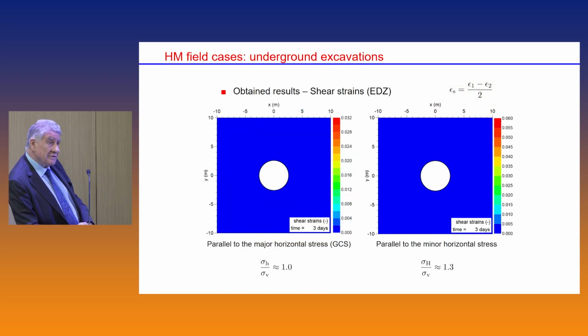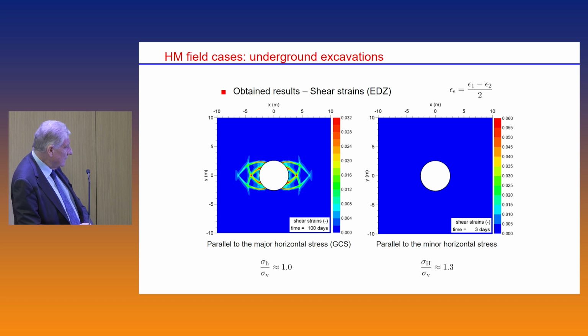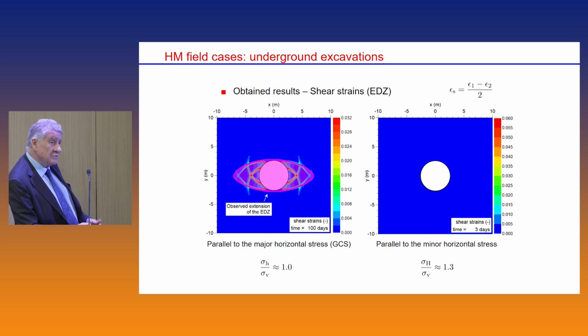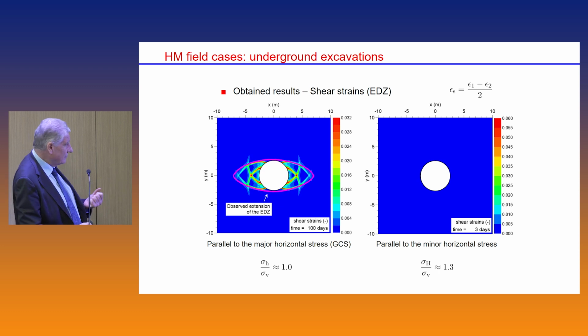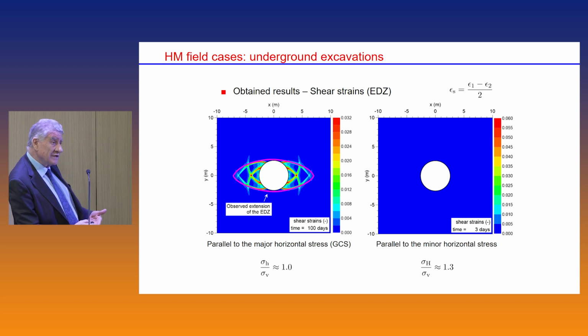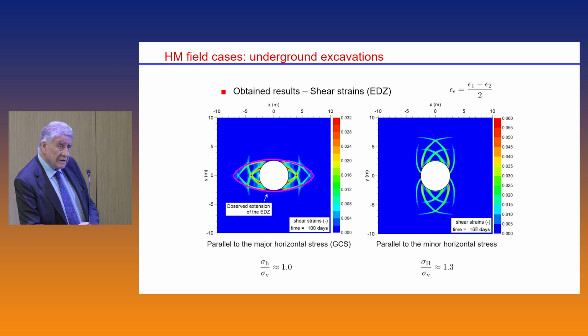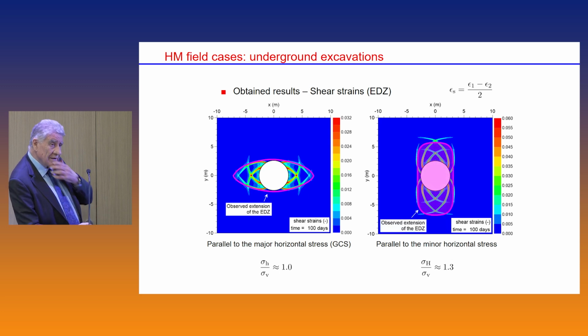Here on the left is the excavation parallel to the major principal stress, so the cross-section in situ stresses are actually isotropic, and we can see how the EDZ develops with these localized zones, ending up with a configuration which is actually quite similar to the one I was showing before, the one that has been observed. If we move now to the right, excavating in the perpendicular direction, now we have a horizontal stress higher than the vertical, and we do the calculations, you can see that now it develops mainly in the vertical direction, again quite similar to the observations.